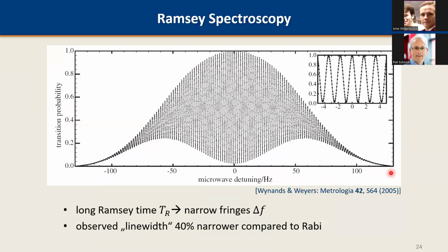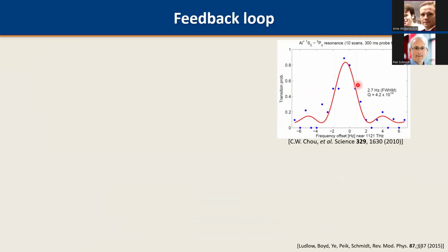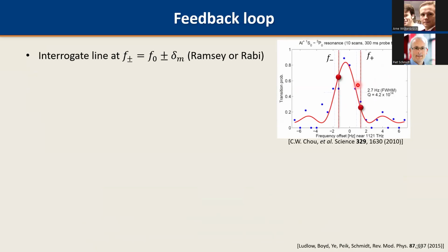Okay. So now we have line shapes that provide us with a slope and a center. We have a center right here, and we have slopes on the side that indicate to us when we're off the center. And now I'm going to show you how we implement that feedback loop, using the example of the Rabi line shape, but it works for Ramsey just as well. What we do, we call two-point sampling. We probe our atomic transition at a specified step, red and blue detuned. Red detuned means lower frequency, blue detuned means a higher frequency, and that step is indicated by delta M here.